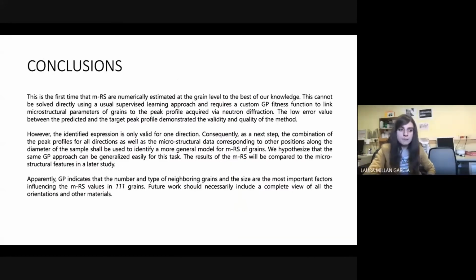So finally, let me sum up our main points. This is the first time that micro-residual stress is numerically estimated at the grain level, to the best of our knowledge. This cannot be solved directly using a usual supervised learning approach and requires a custom GP fitness function to link microstructural parameters of the grains to the peak profile obtained by neutron diffraction. The low error values between the predicted and the target peak profile demonstrate the validity and the quality of the method.